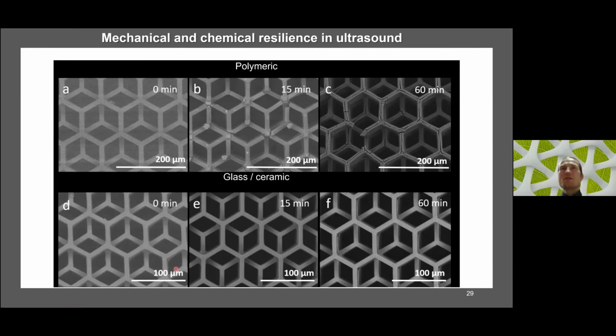So, for instance, if you make a polymeric scaffold and put it into an ultrasonic bath and in piranha solution and shake it for 15 minutes or 1 hour, you see some deterioration and eventually more pronounced cracking, fracturing. Whereas the glass ceramic shows no obvious deformation or fractures, so no cracking, whether again 15 minutes or 1 hour, and as said, kept in a piranha solution.